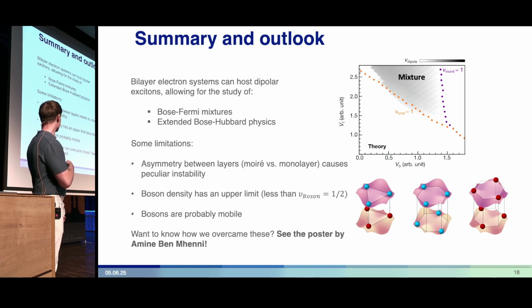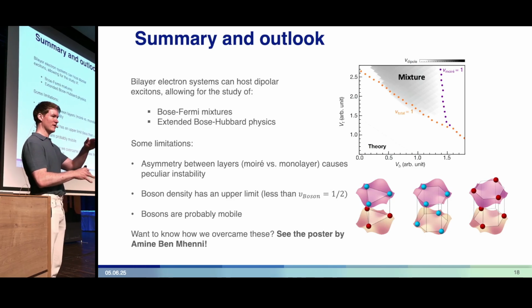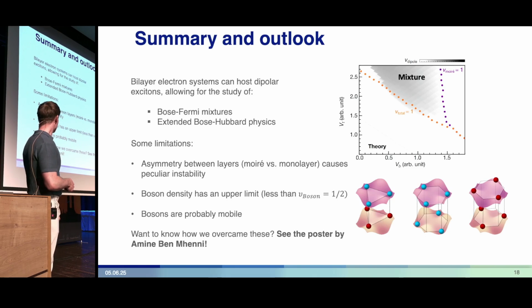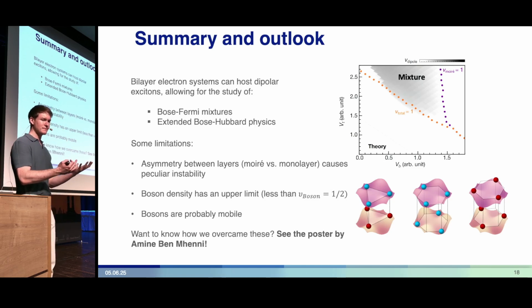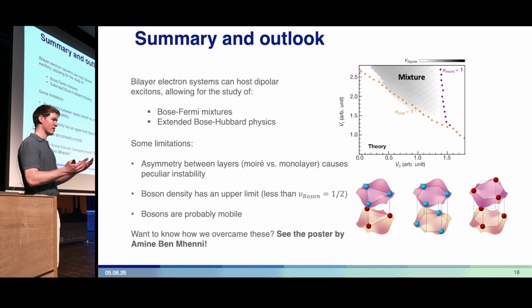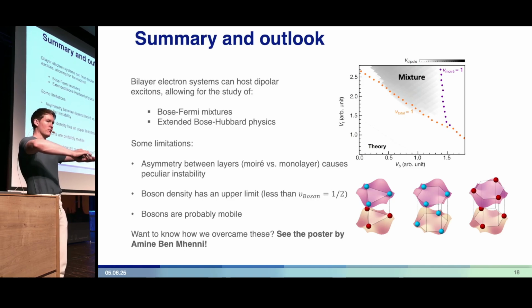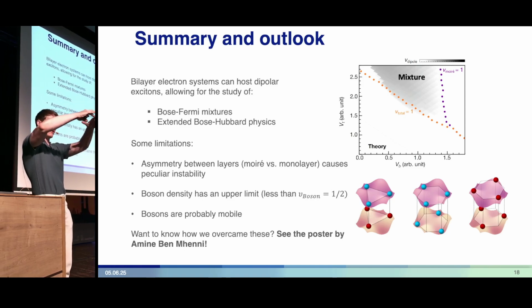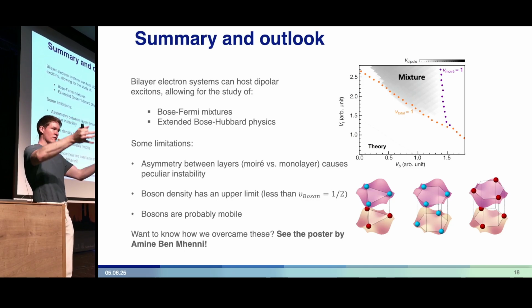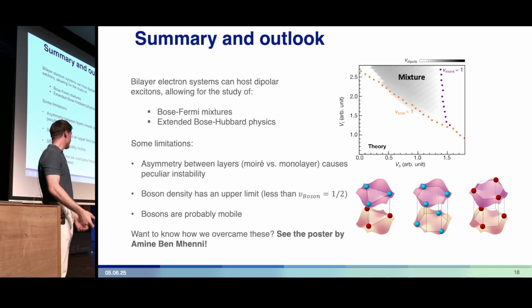The system we study here has this fundamental asymmetry because we have a Moiré layer and a monolayer, which gives us this peculiar doping instability. Also, the boson density has an upper limit, because if I want to achieve a boson filling factor of 1 per Moiré unit cell, I'd have to start with a Mott insulator and then pull all of the charges from the Mott insulator into the monolayer, and then I have no underlying Mott insulator to stabilize the phase.